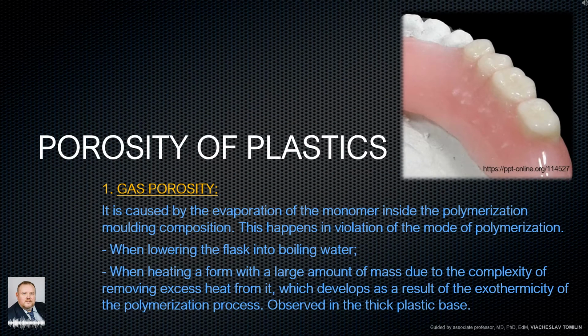Porosity of plastics. 1. Gas porosity. It is caused by the evaporation of the monomer inside the polymerization molding composition. This happens in violation of the mode of polymerization, when lowering the flask into boiling water, or when heating a form with a large amount of mass due to the complexity of removing excess heat from it, which develops as a result of the exothermicity of the polymerization process, observed in the thick plastic base.